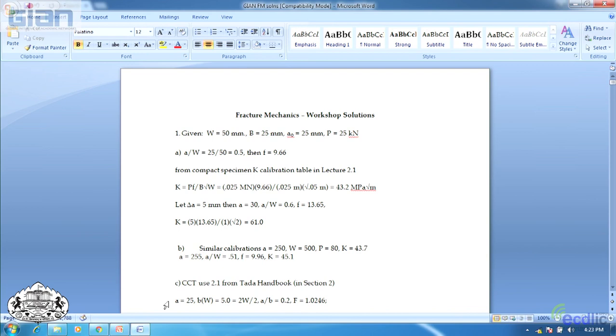Anyway, if you change the crack length by 5 millimeters, then the crack size is now 30, A over W is 0.6, and F goes up. Everything else stays the same in the K calculation, but the F goes up. So recalculating that, the K went up to 61. So you can see just increasing 5 millimeters went from 43 to 61. And it's very dependent on crack size.